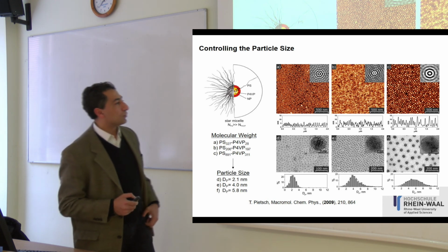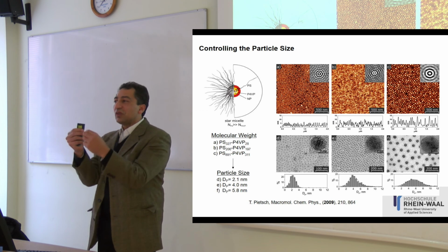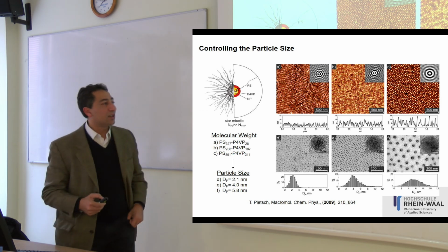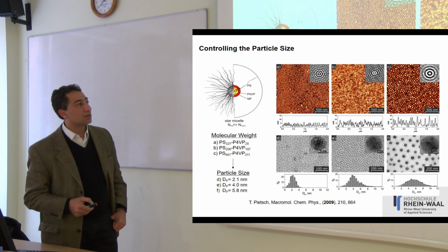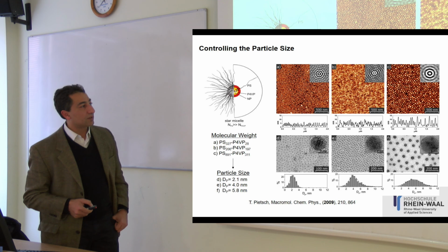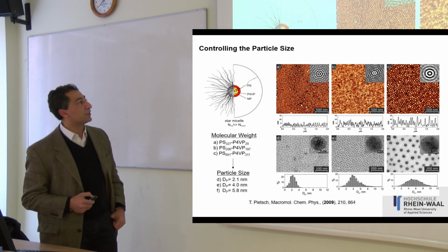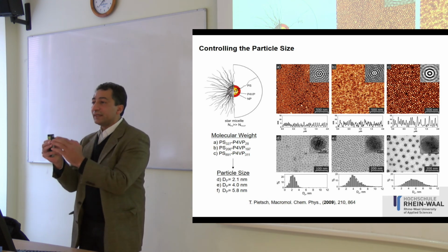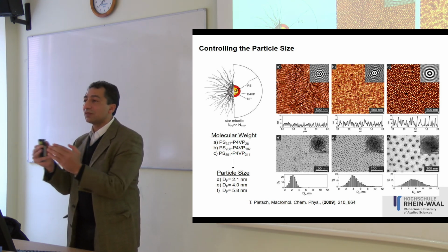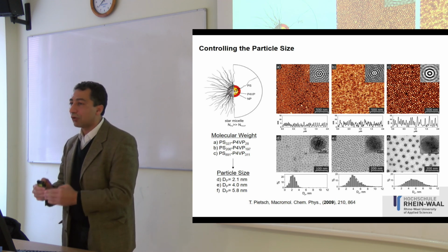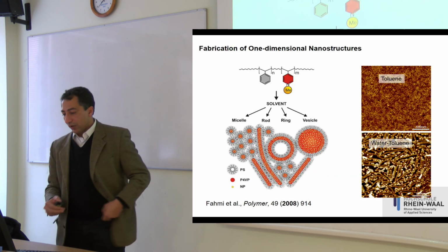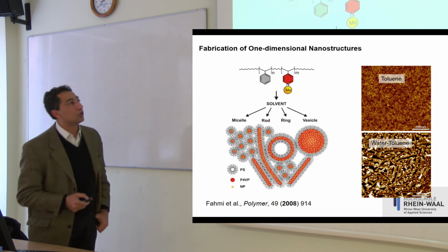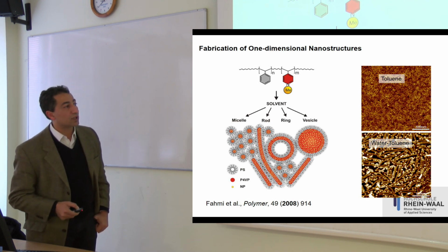The good news is that we can control the distance between these inorganic particles, so we can have access to many levels of functions. We can control the level of the inorganic, we can control the distance between them, we can control the alignment between them. You can just change the polymer length and the volume fraction between these two different polymers in the block copolymer. This is quite interesting. We would like to make not only a 0D structure, we would like to go from 0D structure to 1D structure.